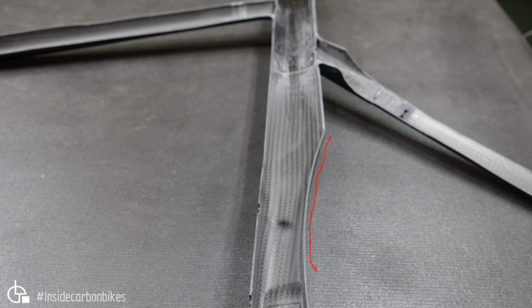So as long as you don't have a leak in the mold, you won't have those sorts of voids like you can get with a prepreg laid up part, which traps those voids within the layers.